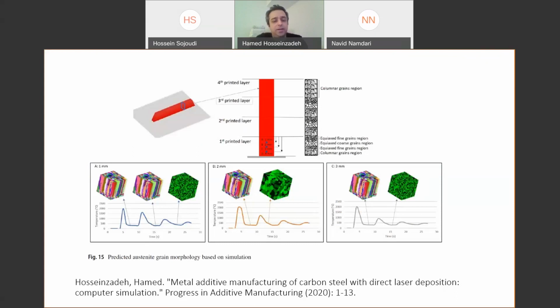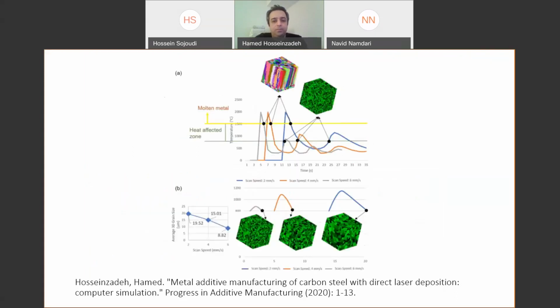extract the heating and cooling curve and calculate the final microstructure for that point and see if it is what we want or not. Or, for example, if it is not, what would happen if we change the scan speed or laser power? Can we revise it or not? And you can see in this graph, if we increase the scan speed, the final grain size is finer. If you want to have a finer microstructure, in this case, we need to increase the scan speed. This is one of the variables that we can change to optimize the microstructure.